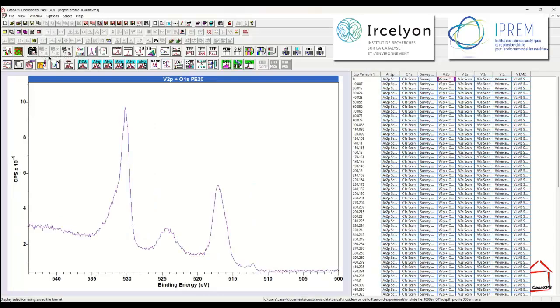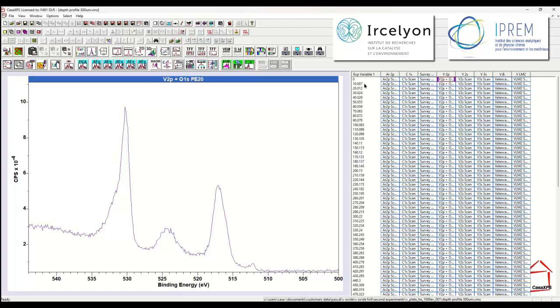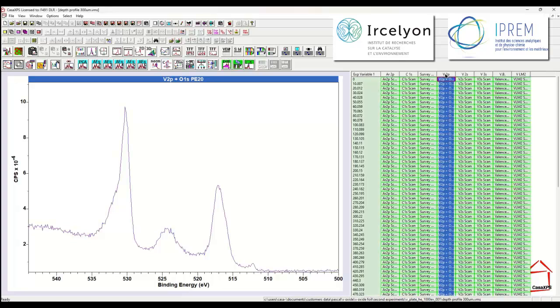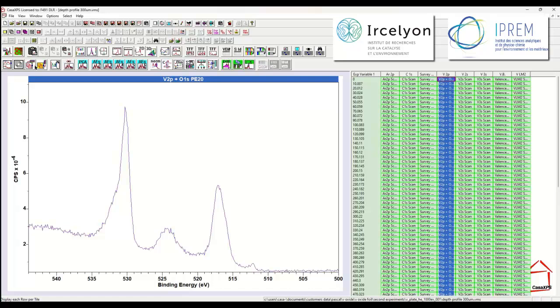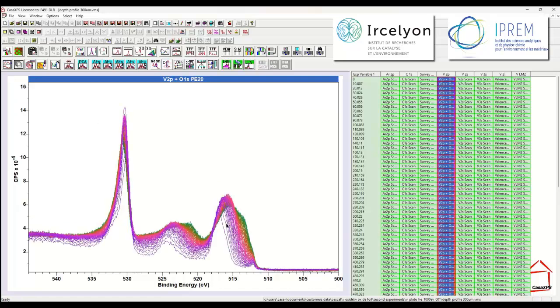This data file is similar in that it's measuring spectra from a vanadium foil. The difference in this case is that between each of the XPS measurements, the surface is irradiated with helium ions of 1000 eV. The result, while it's not apparent initially because the data look very similar to the previous file, once the ions strike the surface, we end up with quite a change in the shape, particularly of the vanadium oxide.